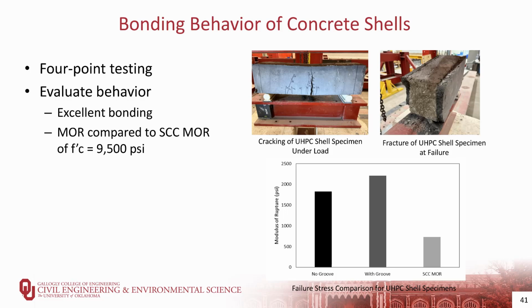And I think it's because we're going to scale it up. Those were 8x8 specimens, and we're doing 9x16 pre-stressed specimens. So obviously those things will add more complexity and complications to the bigger specimens. But that's why we still want to evaluate one that is smooth and the other one with some mechanical anchorages, to see if it's going to make a big difference in the big specimens, or if it's going to be similar behavior to those two trial specimens.